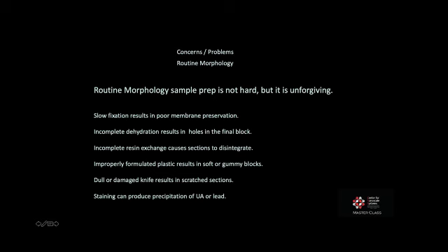If you have an incomplete resin exchange and there are solvents left in the block after it's polymerized, then the sections will disintegrate when they hit the water when you're sectioning and be unusable. Improperly formulated plastic can result in soft or gummy blocks, and you cannot cut soft blocks thinly, so that preparation would be unusable. If you're not careful or if you damage your knife, then you'll end up with scratched sections or just unsectionable